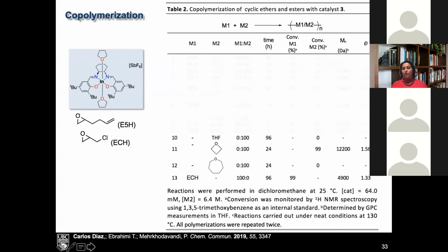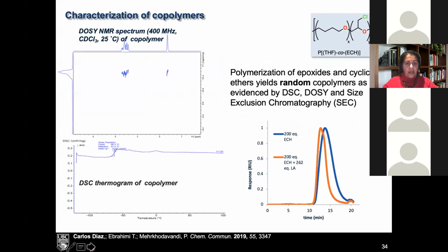He was also able to show that depending on the system, you need to have the epoxide polymerized before you can copolymerize it with the cyclic ethers. They won't polymerize on their own. Again, the key to this chemistry for us was to look at the nature of these systems. In this very first system, what we were getting was random copolymers, random copolymers of inserted epoxide and other cyclic ethers. You can see that by the DOSY, you can see that by the DSC, where we just get one Tg value, and you can see that by the GPC.